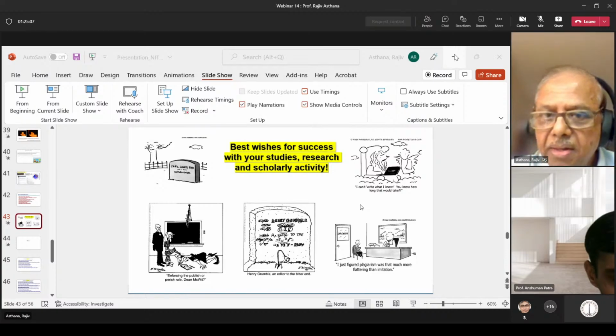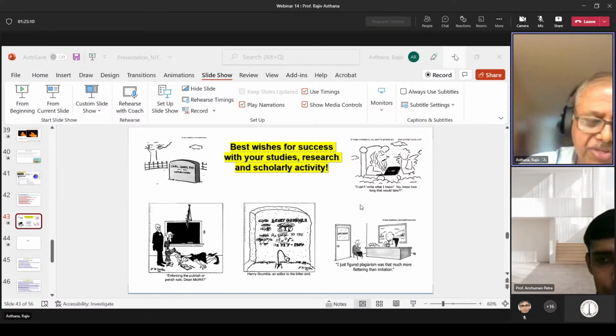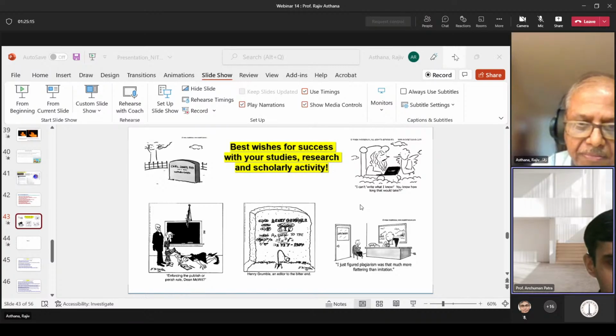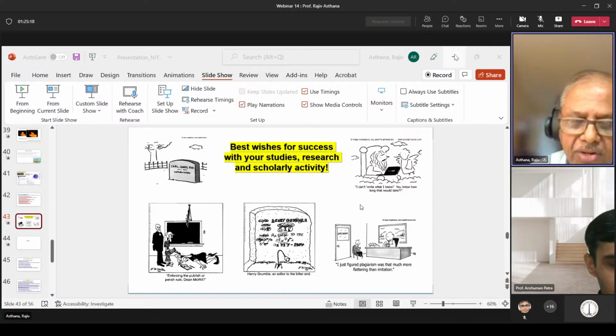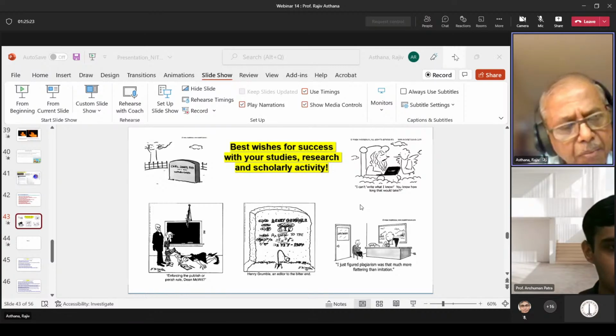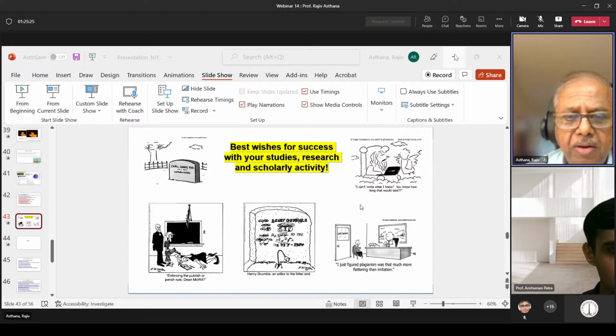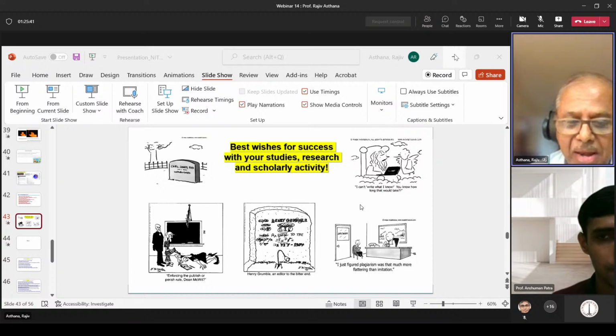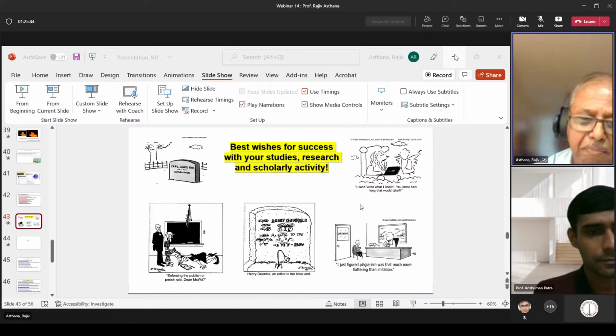Okay, let me get back here. So you're saying that instead of trying liquid phase sintering, you want to infiltrate the system and see whether densification kinetics will be enhanced? Is that the question you have? I'm not sure. I think infiltration may have some challenges, especially if you have a relatively large size component, because infiltration will occur only through interconnected open pores. And that may limit the distance to which your liquid can penetrate the compacted or green part.